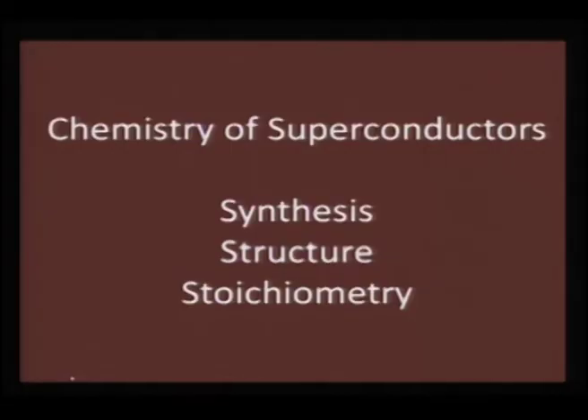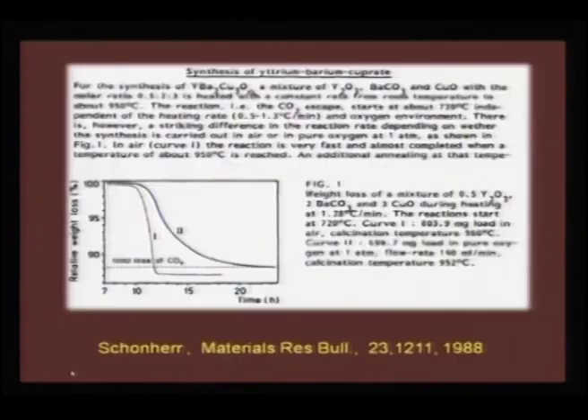Although now any undergraduate lab can perform this experiment, in the initial days it was very difficult to understand the chemistry of this, because even if you miss out a little bit on the synthetic part, you might end up with a non superconducting phase which will be a green compound. So, synthesis is important, and once you have a feel for synthesis, you can try to play around with the structure and also the stoichiometry. I will tell you how everything progressed over the years.